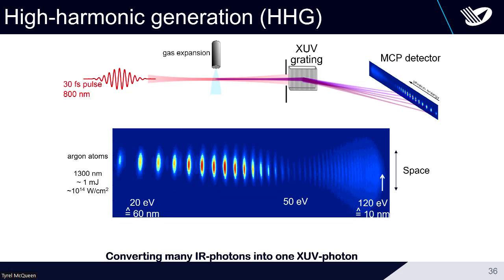So this is done with 1300 nanometer. So what we're seeing here are multiples of the energy. It's about 1 electron volt of the 1300 nanometer. And that goes here from 60 nanometer to 10 nanometer, ultra broadband. It's a huge wavelength range that can be spanned like that.